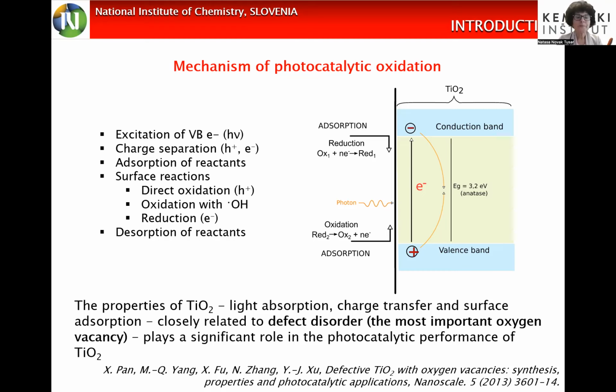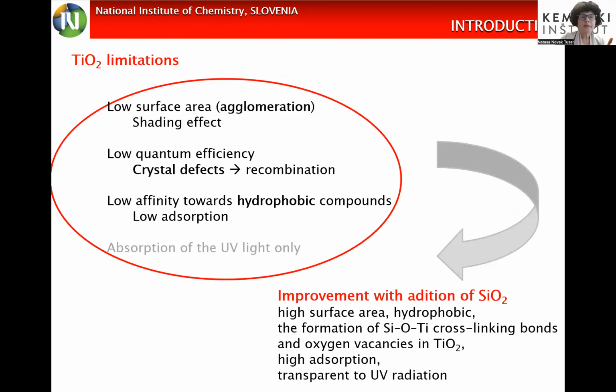Titania properties like light absorption, charge transfer, and surface adsorption are all closely related to defect disorder. The most important defects are oxygen vacancies, and this plays a significant role in the photocatalytic performance of titania. But titania has some limitations: low surface area, low quantum efficiency, and low affinity towards hydrophobic compounds. Also, absorption of UV light only is one of the limitations, but for air cleaning we usually use only UV light in the air cleaning devices. So in this case, this is not a limitation.